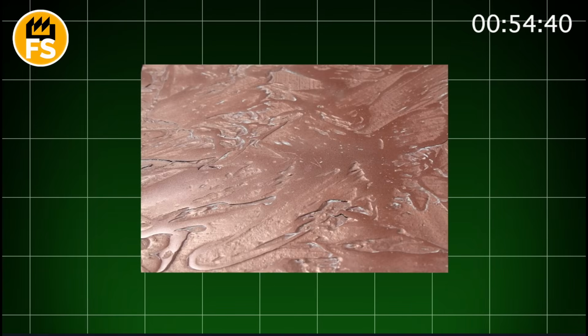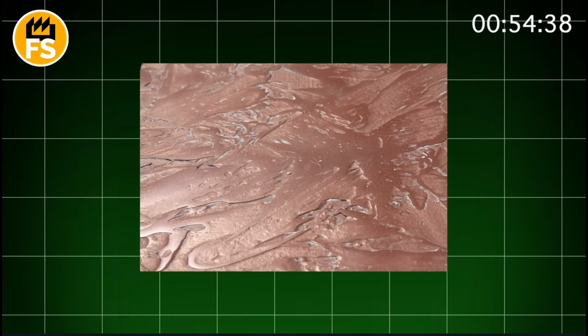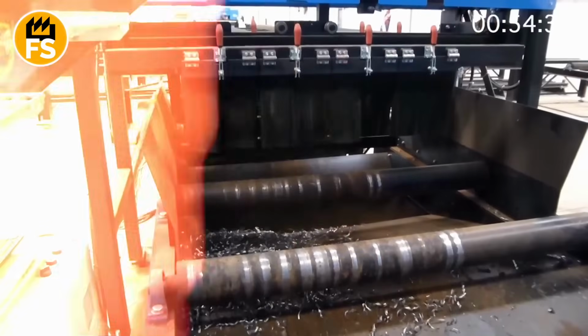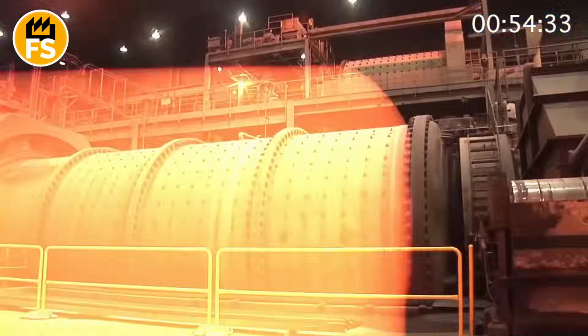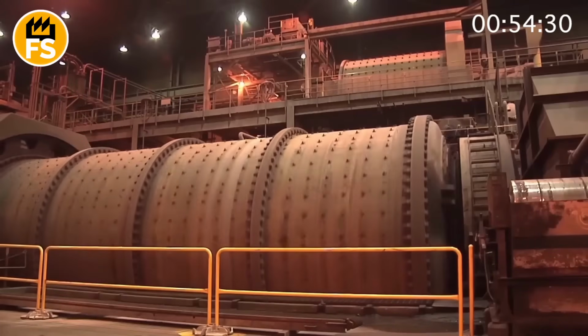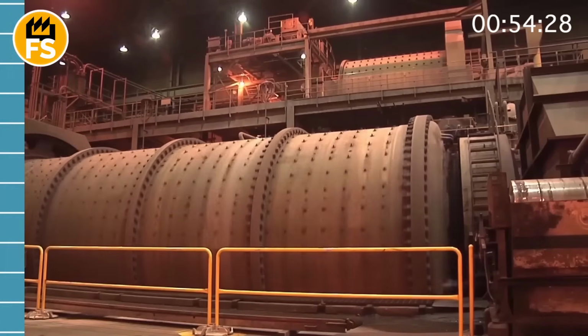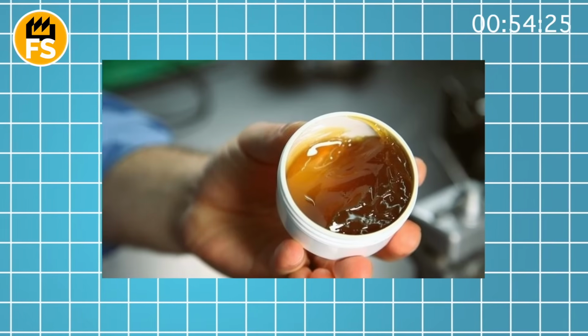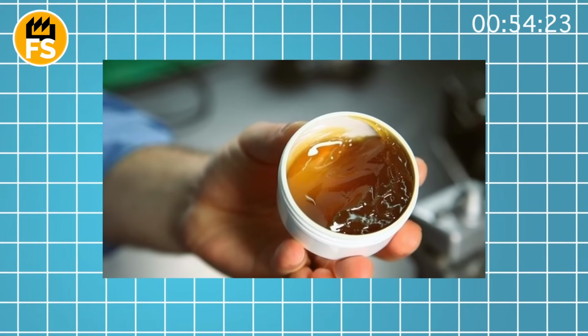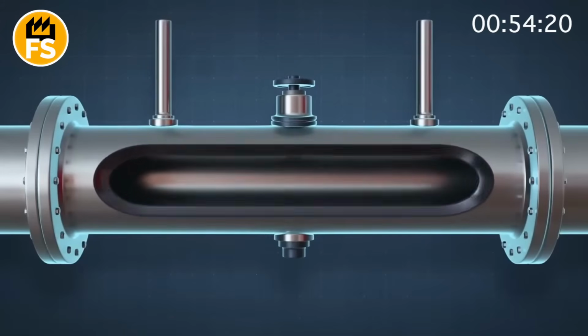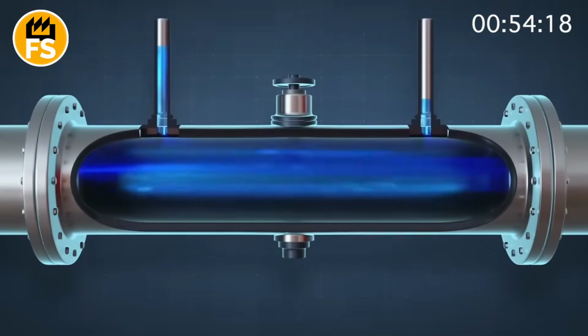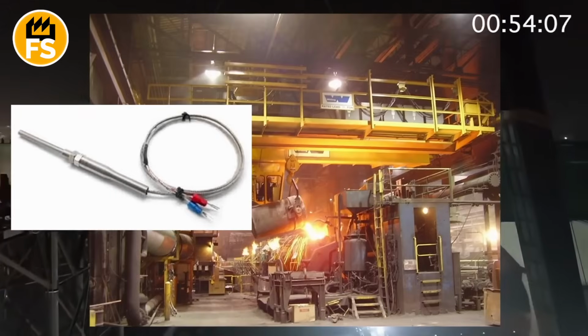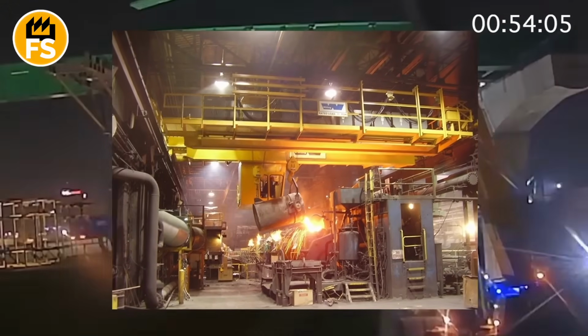The metal in liquid state, shining, heavy. It cannot be touched, only observed through special glasses. One careless movement, and half a ton of molten alloy can spill onto everything around. At this moment, fluxes are added to the melt, powders that help collect slag, meaning impurities, oxides, remnants of old metal. They float to the surface, forming foam or a crust, which is carefully removed. One melting crucible holds up to 10,000 pounds of metal. The temperature inside is controlled by thermocouples capable of withstanding 2,000 degrees Fahrenheit and more.